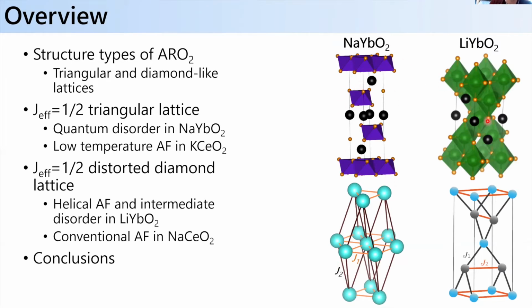And so the second class of materials that I'll be talking to you about is embodied by lithium ytterbium O2, where you can see the structure is dramatically different. Instead you have a connectivity between the ytterbium ions in this system that's what we call a stretched diamond-like lattice structure. And I'll talk more about that later. But again, this is just showing you the lattice connectivity between nearest neighbors, where J1 is in gray and J2 is the next nearest neighbor in orange, okay?